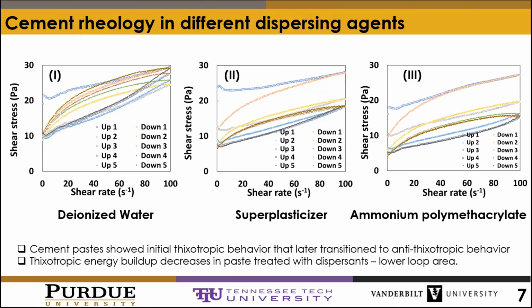So let's discuss cement rheology. The rheology of all cement paste was characterized by a transition from thixotropy to anti-thixotropic behavior in the first 5 cyclical loops. And the thixotropic behavior is typical of a flocculated system, while anti-thixotropic behavior indicates an eventual deflocculated cement paste system. So the stable rheological condition of Portland cement paste under shear is anti-thixotropic, not thixotropic. Also, the thixotropic or anti-thixotropic loop area is a measure of the power per unit volume, that is the time rate of energy storage per unit volume.